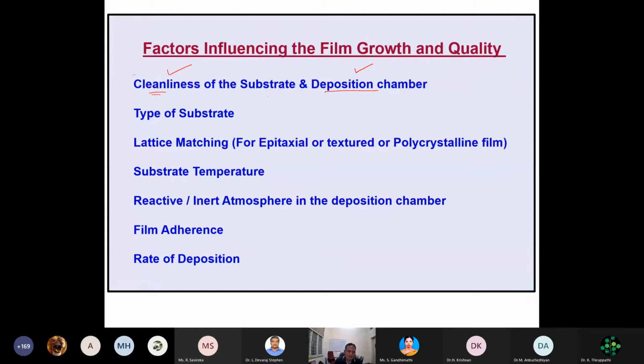Okay, cleanliness is very important because if I have a substrate here and I want to grow a thin film onto it, suppose some kind of dust particle, a bigger dust particle, is sitting here, and I grow a film like this, then you will see that this dust particle sitting here will be a kind of inclusion. So your film will not have good lattice matching here, or some third element or foreign species will be sitting on the surface. Say, for example, oil or sweat from your hand. If you are not handling the substrate properly, that will be a bigger problem for your device, because we are speaking about thicknesses of the order of a few tens to hundreds of nanometers.